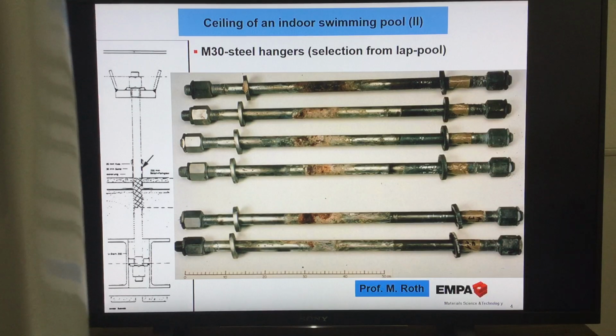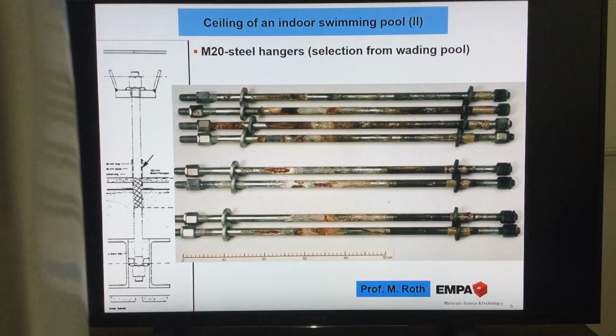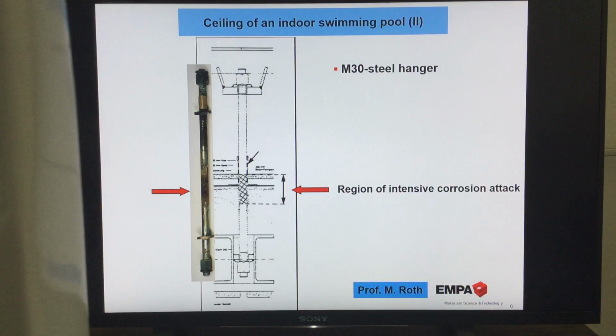Now you see here these steel hangers, some of them were selected from the lap-pool, M30, and everywhere you see more or less at the same spot this corrosive attack. And those from the wading pool, a little bit smaller ones, M20 steel hangers, but again here in the upper middle part we see this kind of corrosion attack. It fits here in this drawing, and you see it correlates quite well with the area which we have seen before on the top.